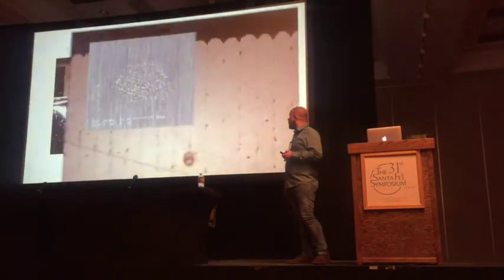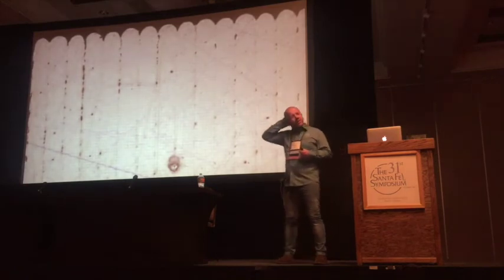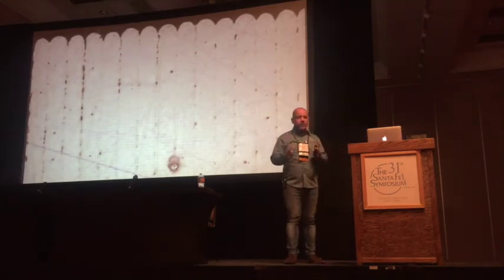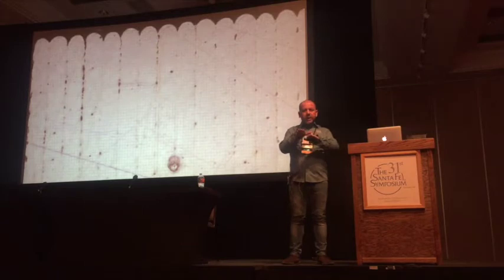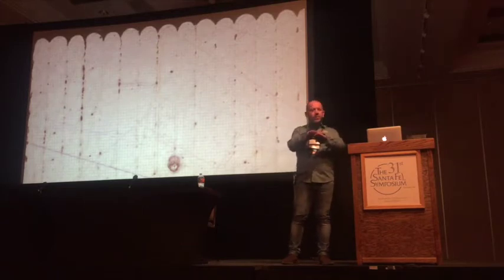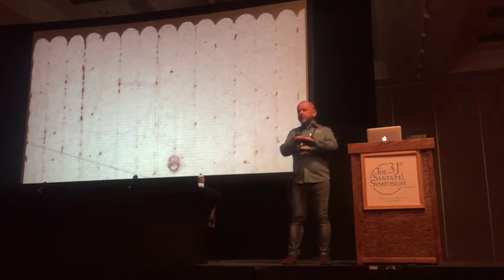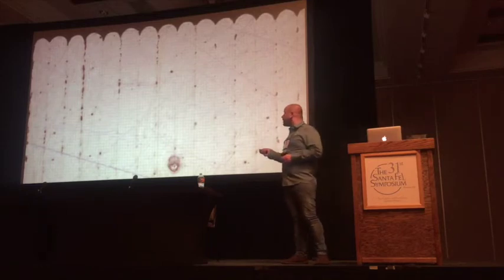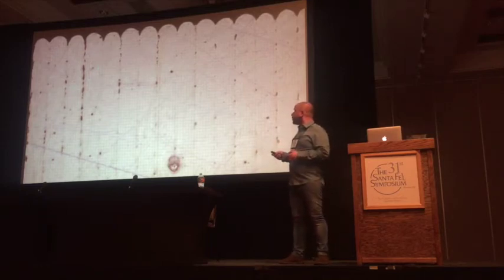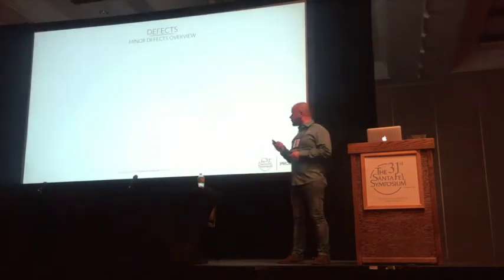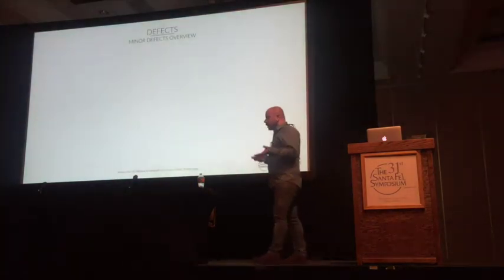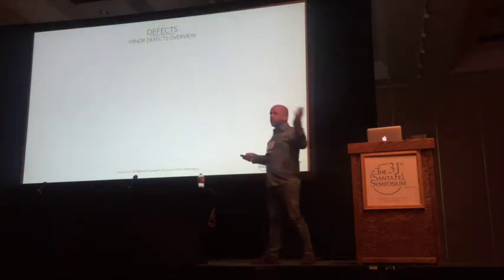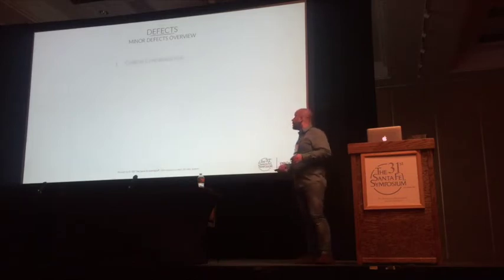Then, okay, this is a typical shrinkage porosity in casting. Then another defect that we could have in 3D metal printing, always connected to the strategies, is that if you do not overlap the melting trace, then there is some lack of melting in the border of the melting trace. And then, talking about some other minor defects that could be in one process or in another one.